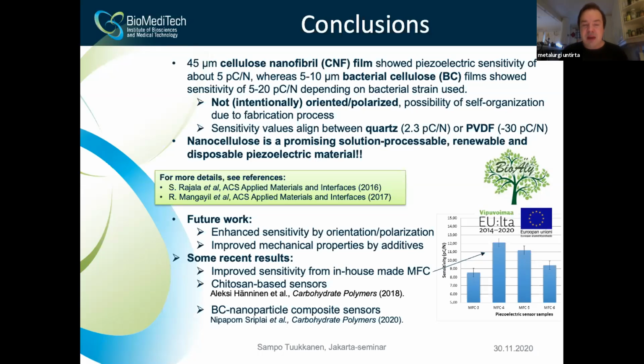What was surprising was that when we mix them, the sensor effect gets lower. So the nanocellulose itself and the chitosan itself give higher values than the mixture. I think, and this is just my speculation again, that when you mix them, it messes up the self organization of the film. That is one explanation, but this could be studied much more. It was an interesting observation.